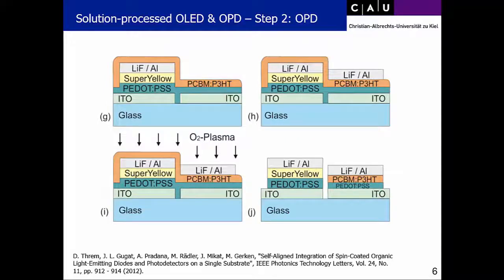So in the second step, then PCBM P3HT was spin-coated, which is a photodetector material. We again added lithium fluoride aluminum cathode and used the oxygen plasma to etch away all of the remaining material that is not protected by the two electrodes, and this way we could obtain, even though we use solution processing, on a single substrate OLED and OPD devices.